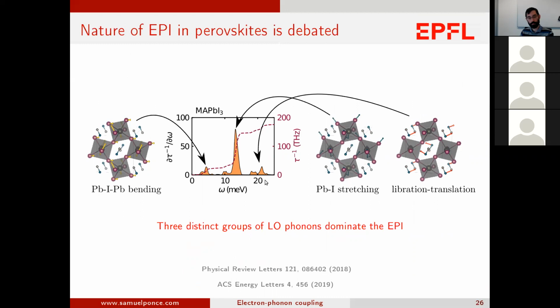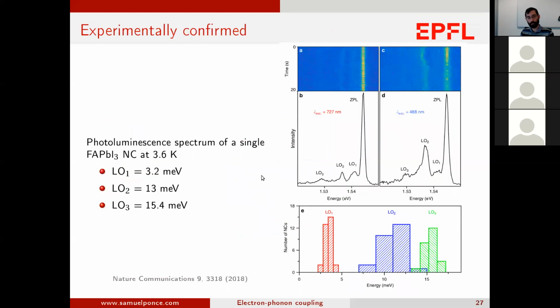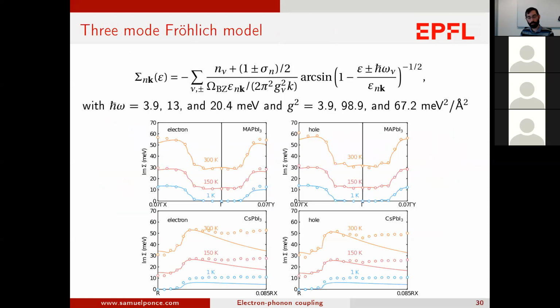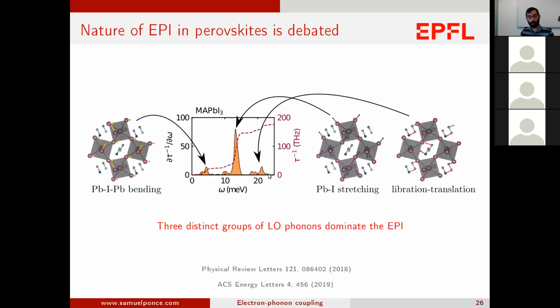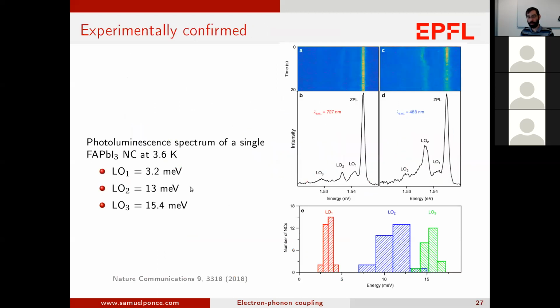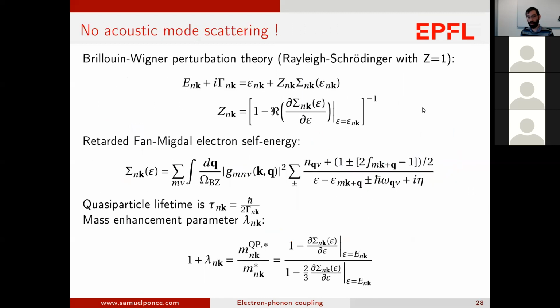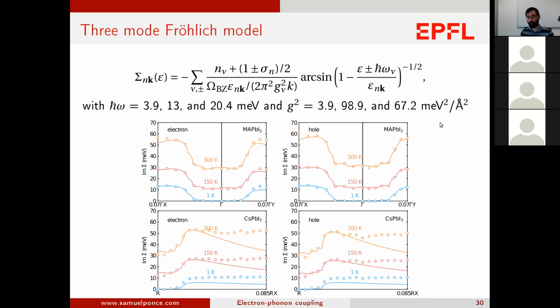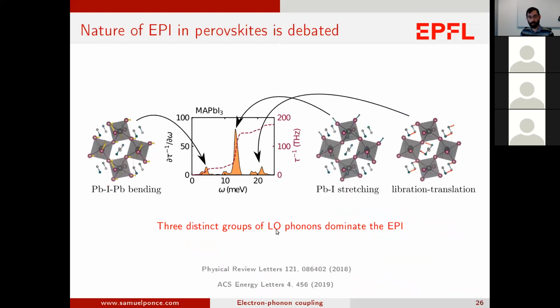Exactly. And you assign a coupling which seems pretty strong compared to this picture, in the sense that if I look at the data you are reporting later on, it is 67. Yeah, the highest one is the second one, and then this one is lower. You see, the biggest electron-phonon coupling is the 13. So this corresponds to 100 cm⁻¹, exactly. So this is the largest coupling, and then you have this one and that one. It's well defined the way we integrate it. If you go to the paper, you will see exactly how we get those numbers. You can directly get them from this picture.